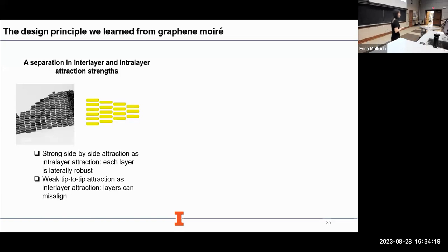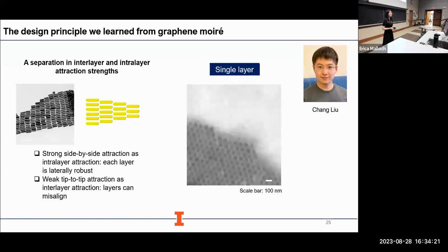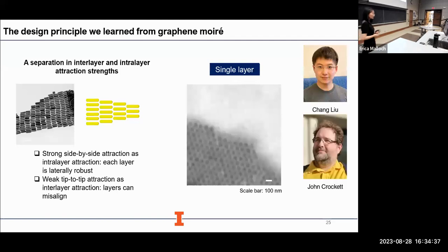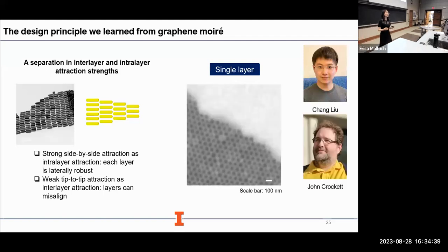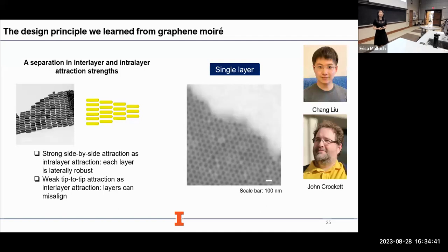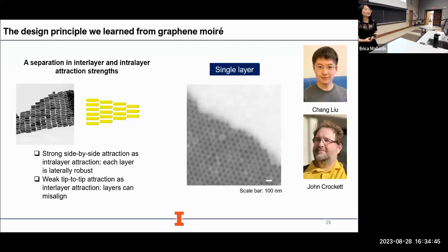So my student Chang adopted the idea, dispersed gold nano rods, put it into liquid phase TEM. But this time he used a magic so that the gold nanorods actually stand against the substrate. So we are looking at the projection view. That's why each nanorod now actually looks like a dark circle. So still in this movie, indeed they form into a hexagonal lattice. And then my student John greatly expanded the level of gold nanorods.